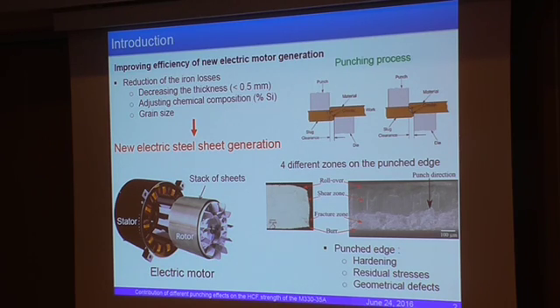Moreover, due to the production rates, all electrical sheets are punched. And as you know, punching is introducing some defects on the edges. So here is a typical morphology you get on the edges, with a rollover, a shear zone, a fracture zone, and a burr. Regarding fatigue, we will be interested in these 3 effects, namely the geometrical defects, as you can see here, but also hardening and residual stresses.